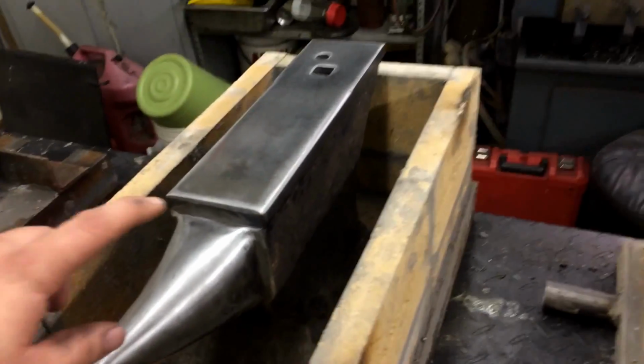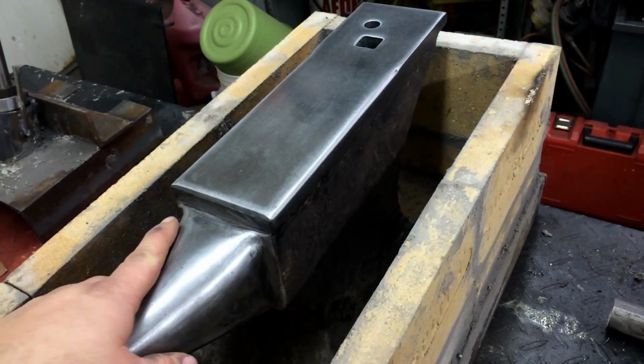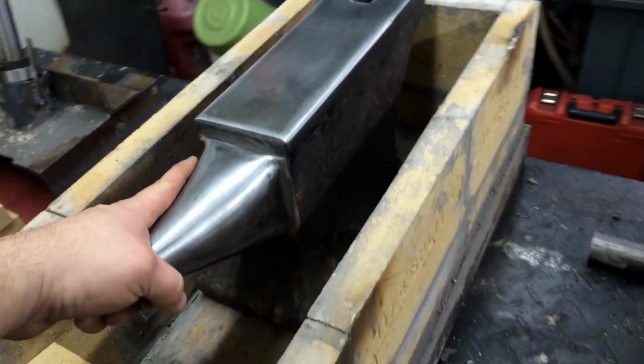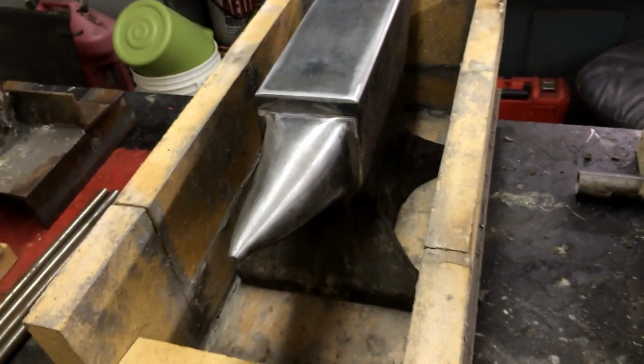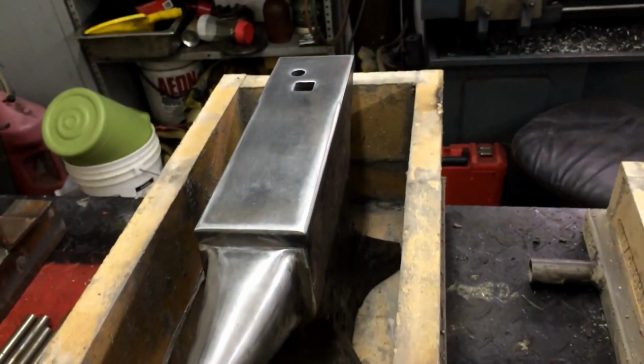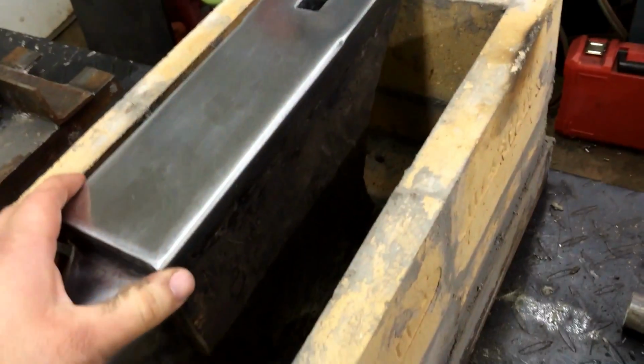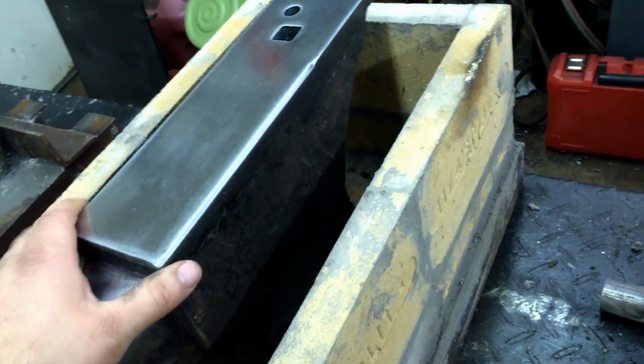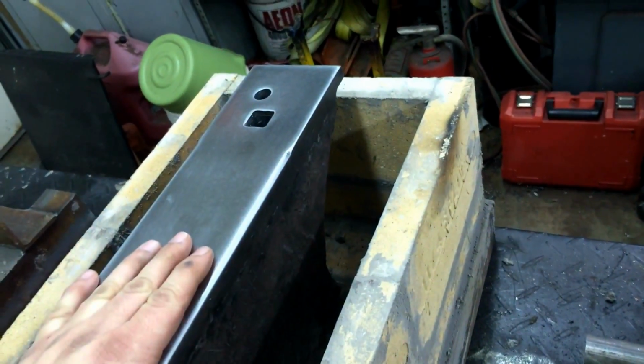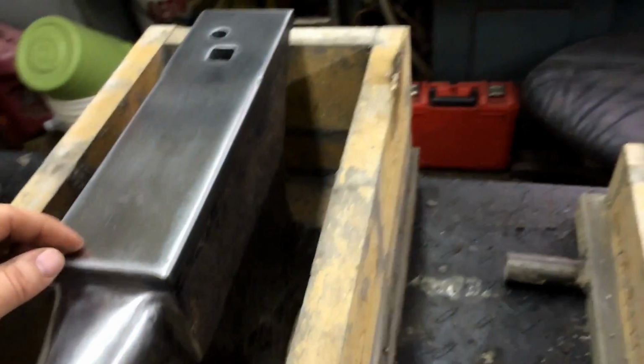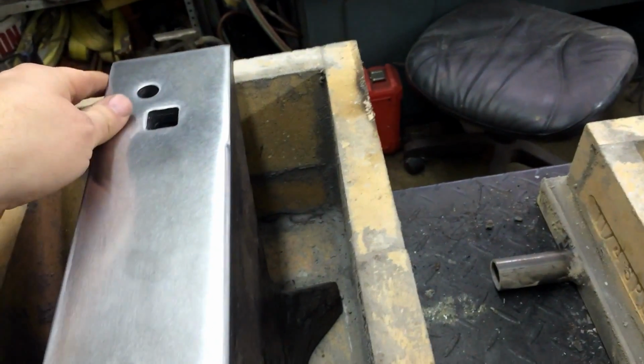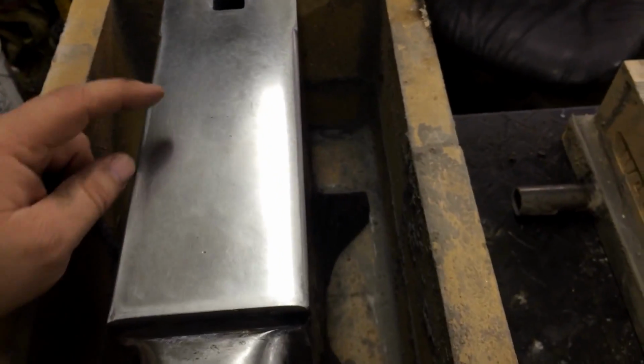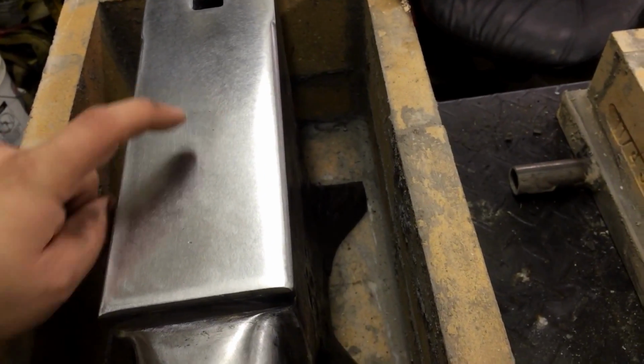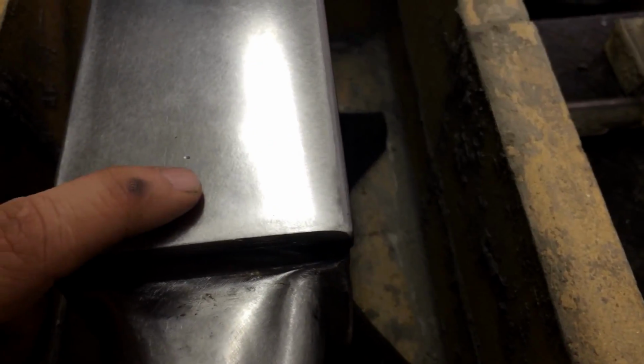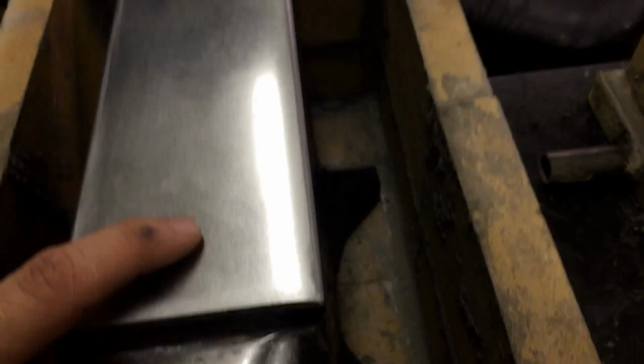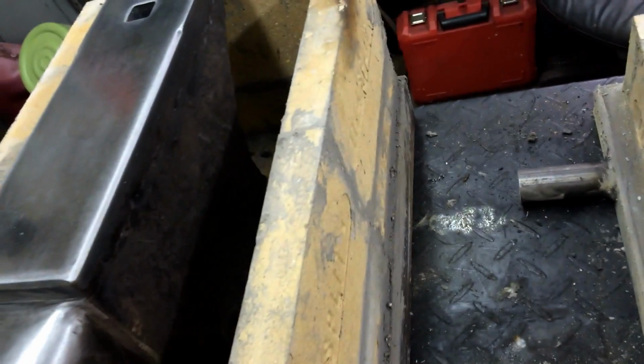But this old anvil, the cutting table on it, had one side of it cracked off, chipped off. So I ended up just removing it and had to rebuild the tip on it. I put this piece of plate, 3/4 inch thick, and I have milled it, trued it up. I put a radius around this, except for the back probably 1/3 of it, and if you can see it just right, you'll see where I plug welded it. You can see where it's pulled some porosity up from welding on this wrought iron. The rest of this is wrought iron.